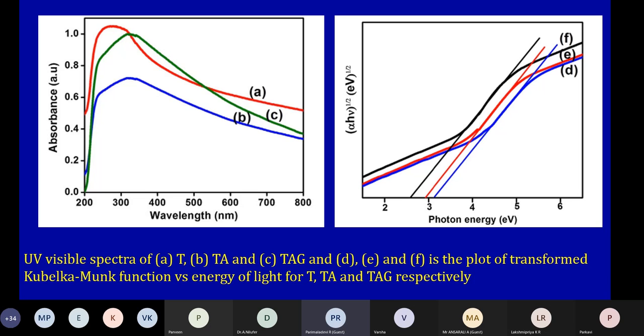This may be due to graphene oxide, which normally has a tubular or lamellar structure that contains unpaired pi electrons that can bond the free electrons at the surface of titanium oxide. So it results in a reduction of the band gap.